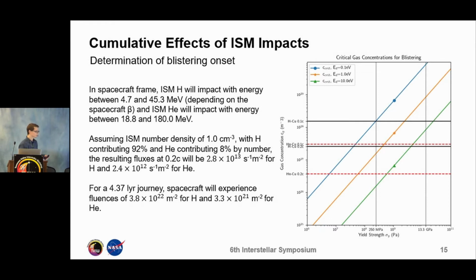So for this analysis, we assume an ISM number density of 1 per cubic centimeter, just for simplicity, and with hydrogen contributing 92% and helium contributing 8% by number, the resulting fluxes at 20% of the speed of light are 2.8 times 10 to the 13 per meter squared per second for hydrogen, and for helium, it's 2.4 times 10 to the 12 per second per meter squared.